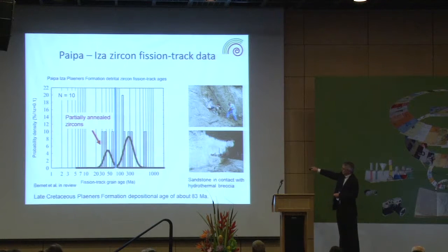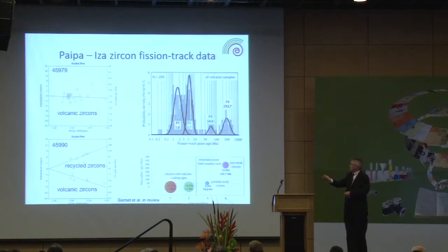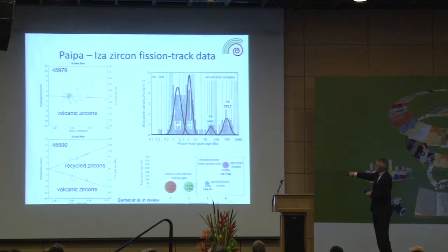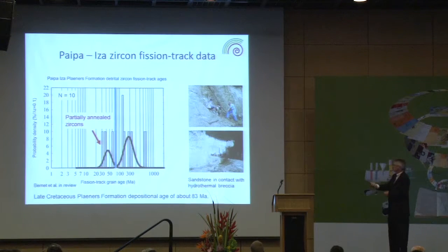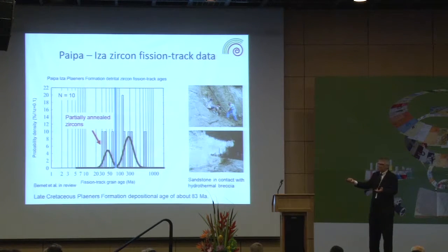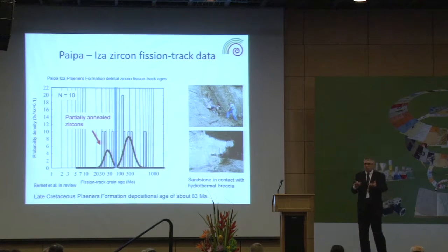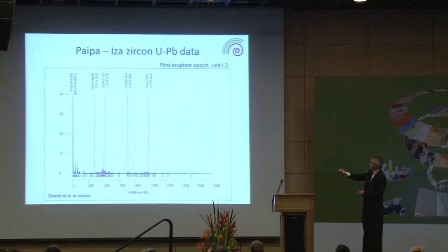And this one is just the recycled ages. So this is how we can attribute that these grains are partially reset and these ones are non-reset. But a strong volcanic signal that corresponds to these ages. Because as I said, for the fission tracks, you need temperatures of at least 240 degrees to anneal them completely. And many of these grains have probably been in the magma chamber.